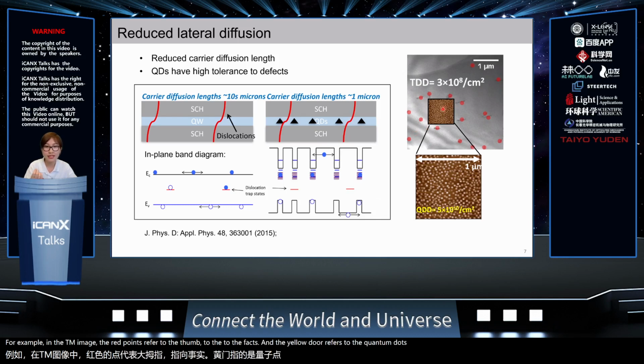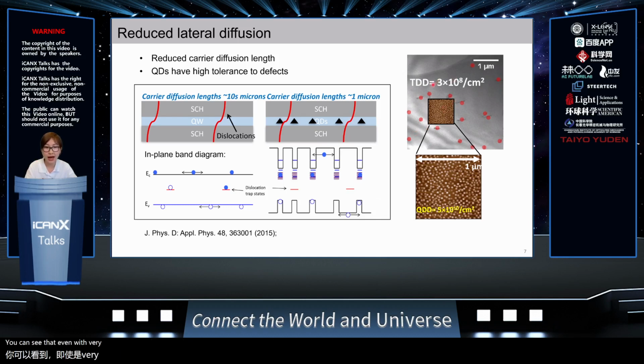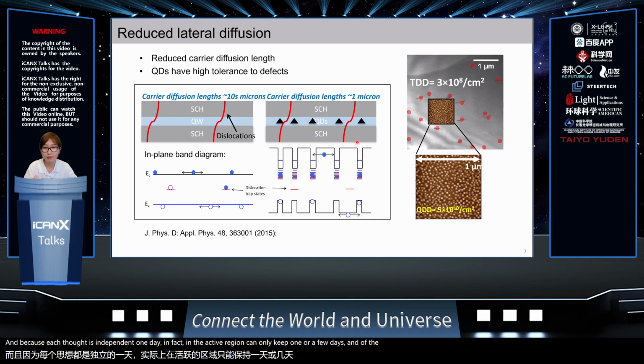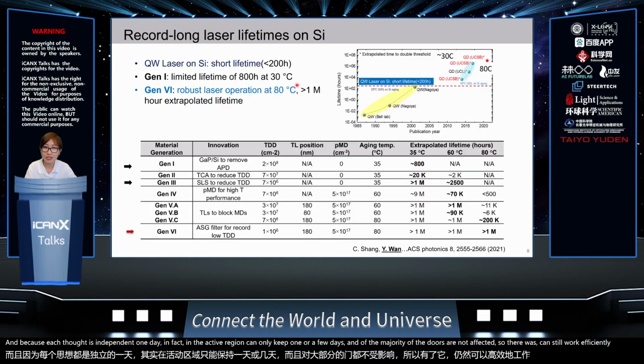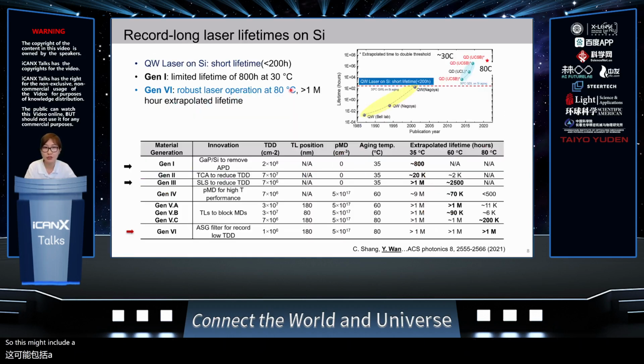You can see that even with this very high threading dislocation density, the dot density is still more than 2 orders of magnitude larger, and because each dot is independent, one defect in the active region can only kill one or a few dots. The majority of the dots are not affected, so the device can still work efficiently. This much improved defect tolerance gives rise to record long device lifetime on silicon.